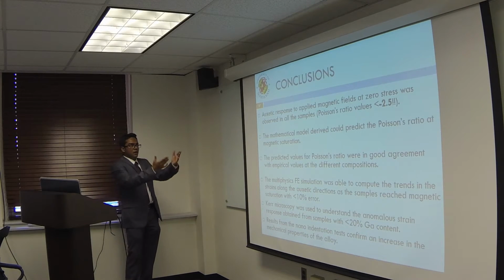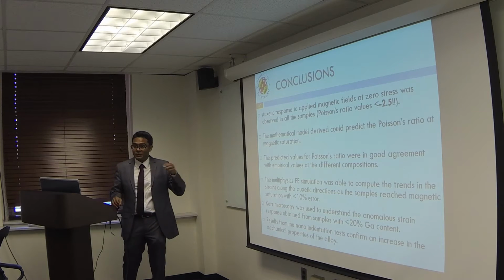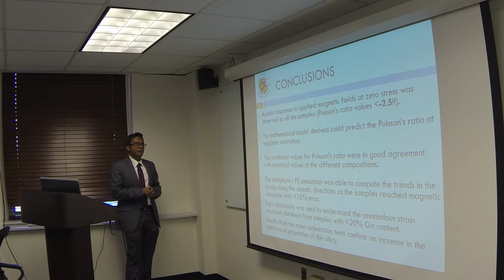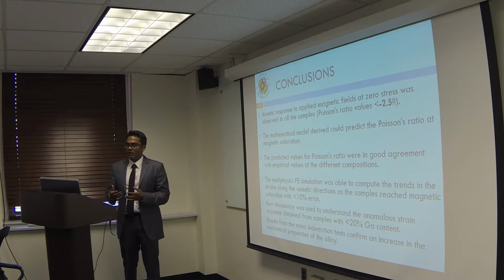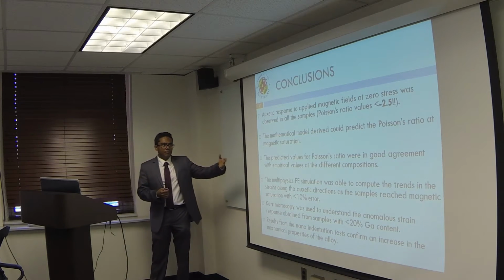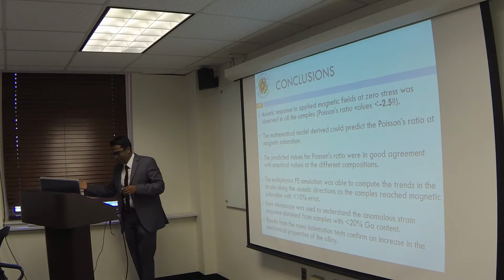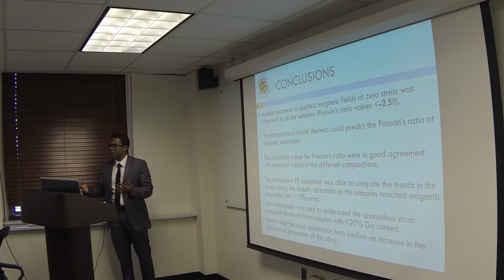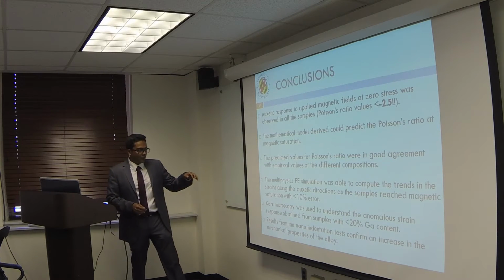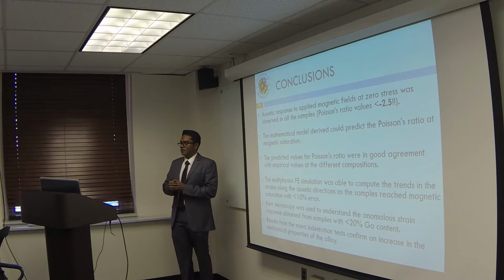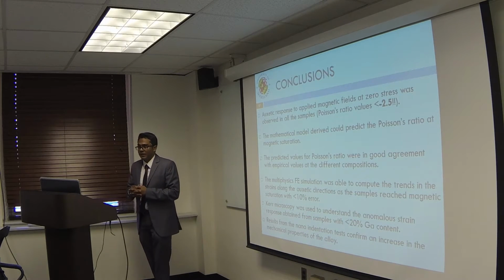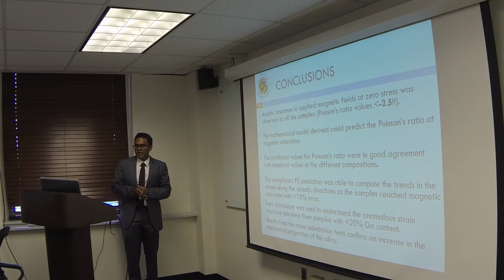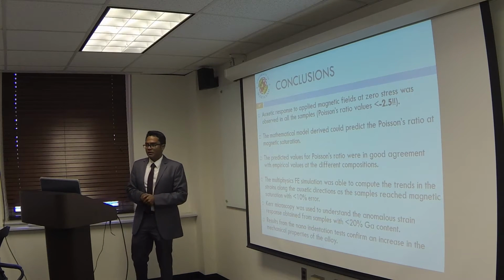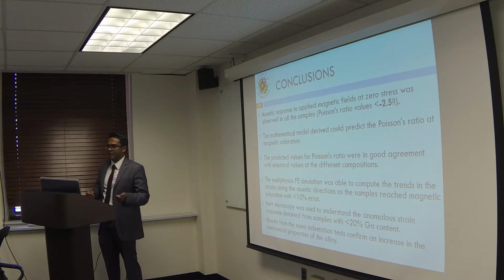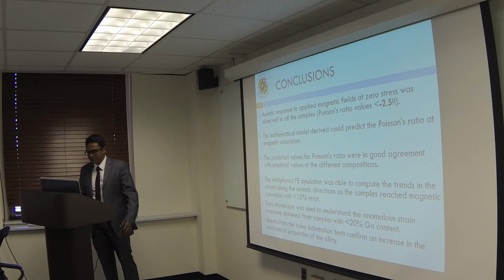So in conclusion, we observed a Poisson's ratio value of less than -2.5 in Galfenol. And we were able to develop a mathematical model that could predict the value at magnetic saturation. The predicted values from the analytical model and the multi-physics simulation were in good correlation with the values that we obtained from the experimental data. We were able to use Kerr microscopy to understand the evolution of magnetic domains while the samples were exhibiting a negative Poisson's ratio. And we used results from nano indentation to prove that there is an increase in the mechanical properties when we reach values close to -1 in auxetic Galfenol.